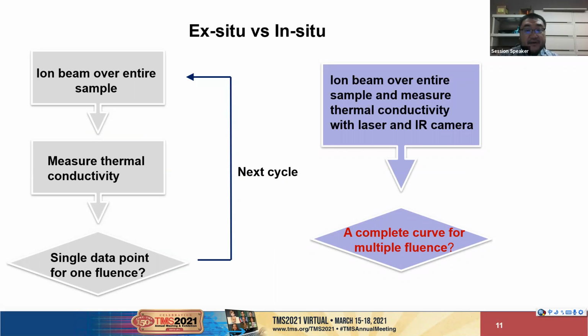Okay. Here is the comparison of ex-situ irradiation and in-situ irradiation. For the ex-situ irradiation, this is the flow chart. First you need to do the beam radiation over the entire sample, and you take the sample out after the implantation to do the thermal property measurement. After that, you are going to get one data point, right? And if you want to get the trend of the thermal conductivity as a function of radiation, you need to repeat it again to get the thermal property for another fluence. So you have to move to the next cycle. And you are going to get the second data point, and again, to get the entire curve, it is going to take weeks, months, or even years.